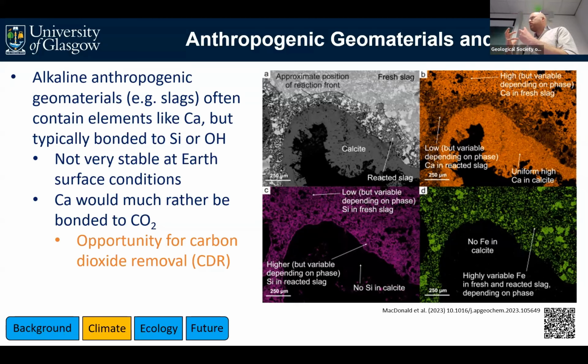And so what this is doing is showing us evidence that we've got this calcium-rich fresh slag when it's come out of the furnace, but it's been deposited and just left to do its own thing in Earth surface conditions. And what's happened is some of the calcium has leached out, essentially, through reaction with water from the edge of these slag particles. It's reacted with CO2 from the atmosphere to form a new mineral, calcite, and that is mineralizing CO2 from the atmosphere. And we can see evidence of that process through this scanning electron microscopy analysis.